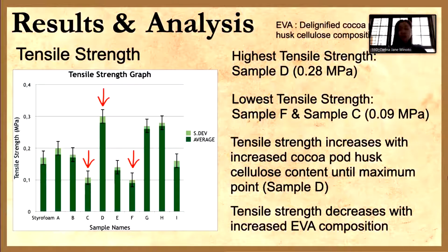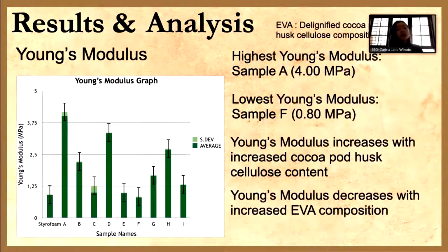the lowest. Continuing on from the graph, it can be stated that increased cocoa pod cellulose content does increase tensile strength values until a maximum point, which can be predetermined as sample D before decreasing even further. However, for increased EVA composition, tensile strength decreases always. Indirectly affected by tensile strength is its Young modulus. The highest Young modulus value was found within sample A at 4 megapascals, while the lowest was found in sample F yet once more at 0.8 megapascals. Such low results in sample F may be attributed due to the combined properties of increased EVA composition and way too much cellulose content.